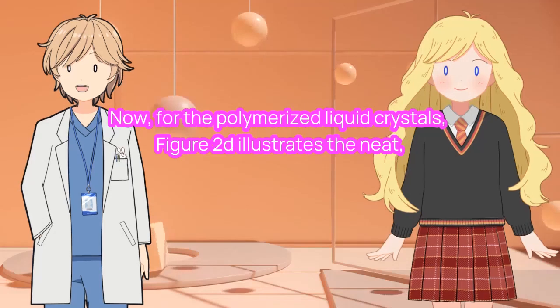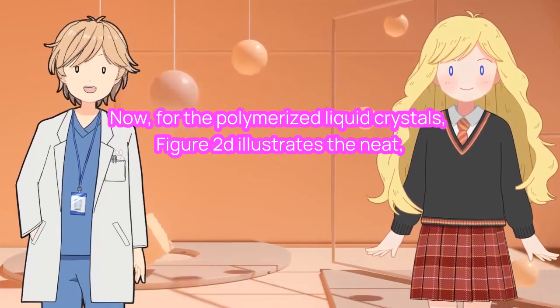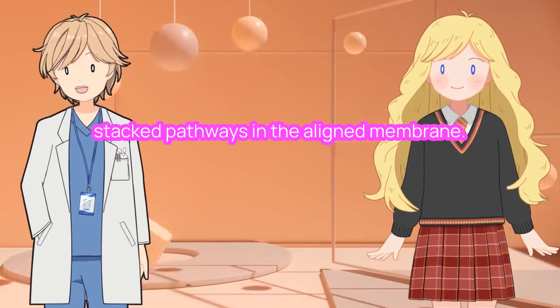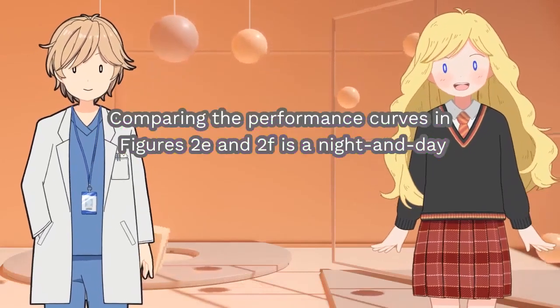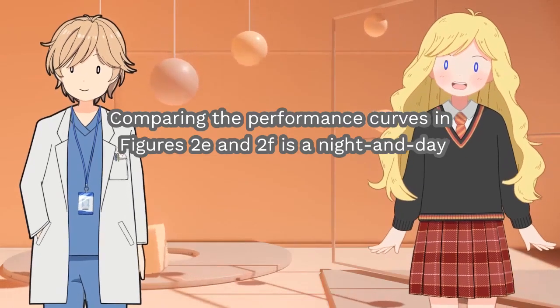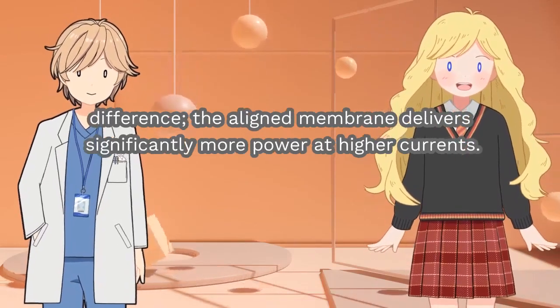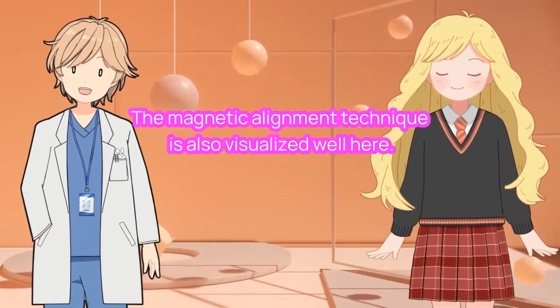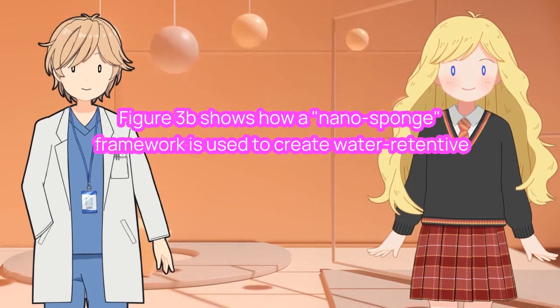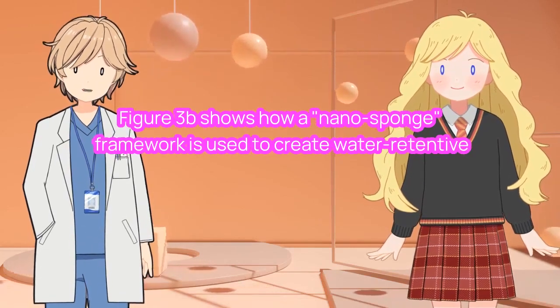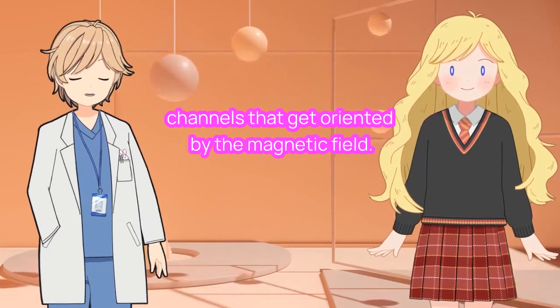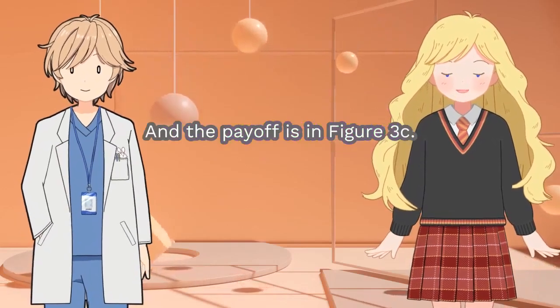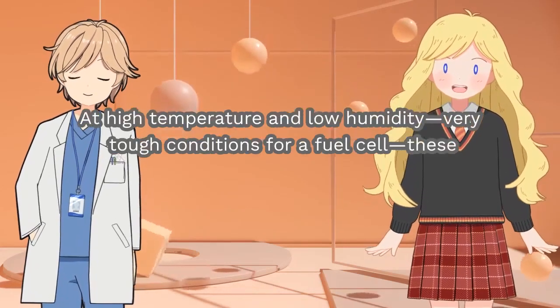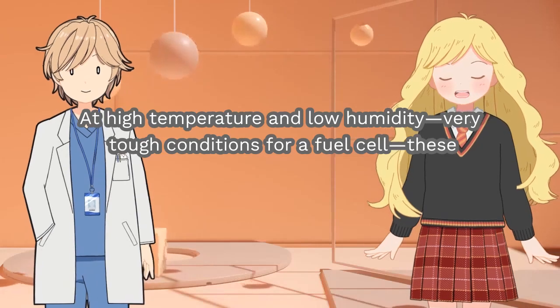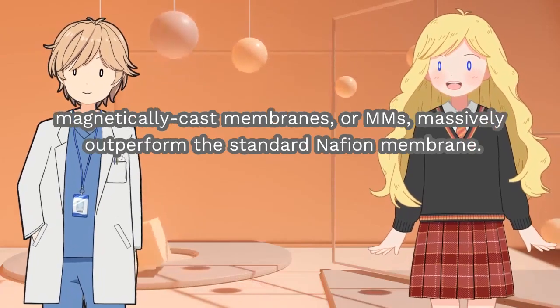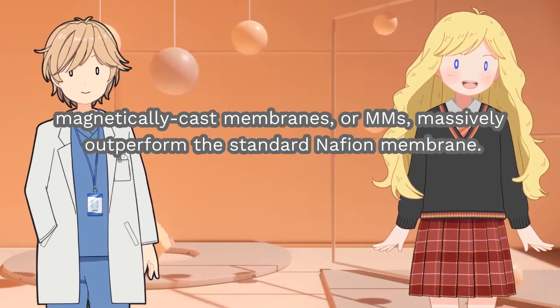Now, for the polymerized liquid crystals, Figure 2d illustrates the neat, stacked pathways in the aligned membrane. Comparing the performance curves in figures 2e and 2f is a night and day difference. The aligned membrane delivers significantly more power at higher currents. The magnetic alignment technique is also visualized well here. Figure 3b shows how a nano-sponge framework is used to create water-retentive channels that get oriented by the magnetic field. And the payoff is in Figure 3c. At high temperature and low humidity, very tough conditions for a fuel cell, these magnetically cast membranes, or MMs, massively outperform the standard Nafion membrane.